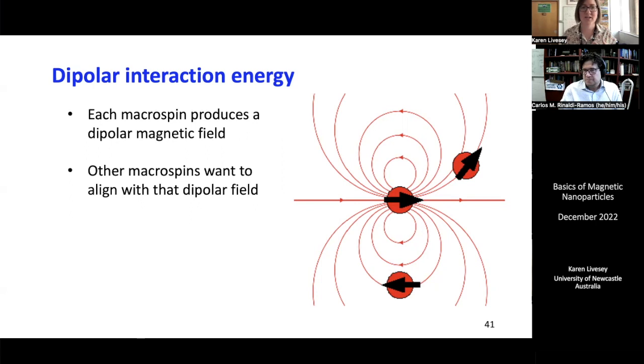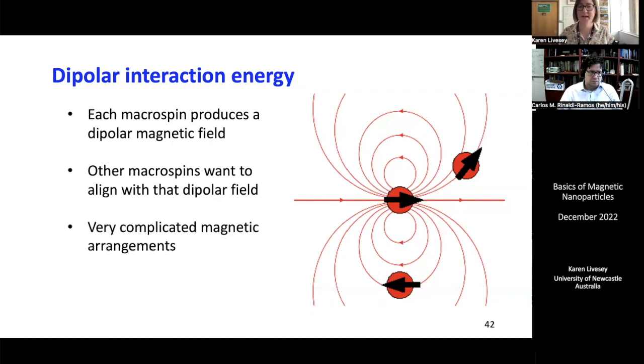This energy contribution is by far the most difficult to treat. And you might get a feeling for that already just from this cartoon, because depending where I put the neighbors, my moment wants to point in a completely different direction. So it's very hard to predict what the dipolar interaction energy is going to do to a nanoparticle, because it really depends on where the neighbors are, how far away they are, and in which direction relative to the moment they are. So this is our most complicated one, and there's still a lot of open questions about how we treat this correctly when we're doing measurements on bulk magnetic nanoparticle samples.